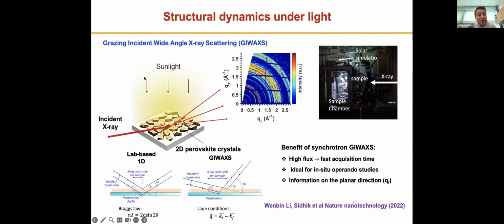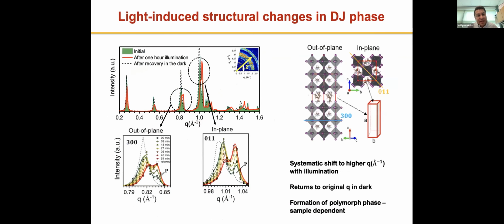And we set up a solar simulator on the 8-ID-E beamline, and then had a temperature control stage. And we looked at grazing incidence WAXS measurements as a function of illumination. And so as we were looking at this, if you take one of the line cuts from these GIWAXS patterns that we get over time, we found something quite interesting.